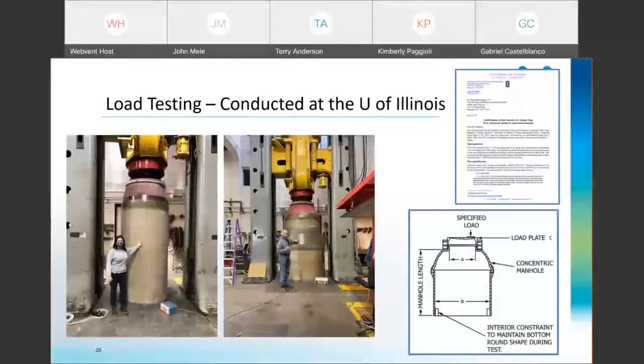The real proof of performance lies in the load testing. Two tests were performed on the completed system. The first, a 48-inch diameter riser section with a 24-inch concentric opening, and the second, a 72-inch diameter riser with a reducing section to 60-inch diameter and a 30-inch cone opening.